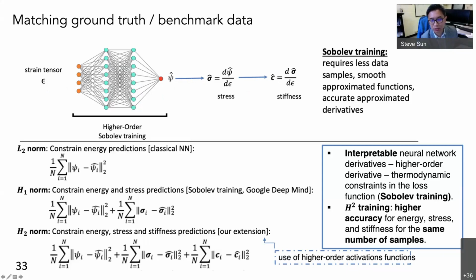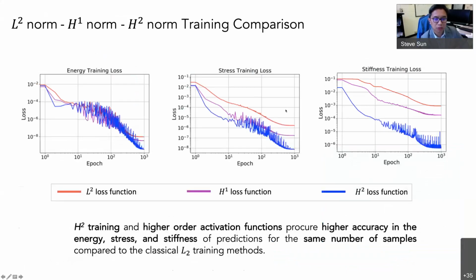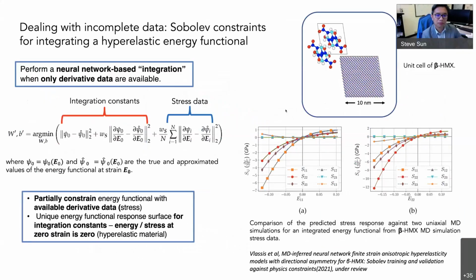The advantage of including the stiffness and the energy is that when we include the energy, we can check the physical property of the energy. For example, we can enforce convexity. And the good thing about incorporating the stiffness is that it is similar. We can also check the ellipticity and then the stability of the energy functional. So this is some of the response that we can get in the training of the elastic energy functional. We found out that using a high order objective function helps not only in generating a better stiffness, but also in generating better stress and energy, even though the minimization includes the stiffness term instead of just the energy term.